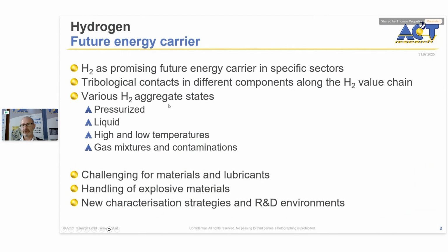It can be present in different aggregate states. It can be under high pressure. It can be liquid. Depending on the aggregate state, it can be hot or it can be very cool with low temperatures in case of liquid hydrogen. It can be pure, it can be present as gas mixture, and it can be contaminated. And all this has effect on the tribological contact and behavior. So it's actually challenging for materials and lubricants. With a mixture with oxygen, it's explosive. So there's a need of new characterization and R&D environments.